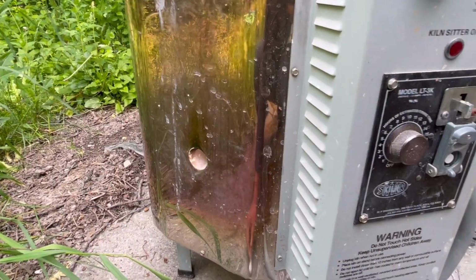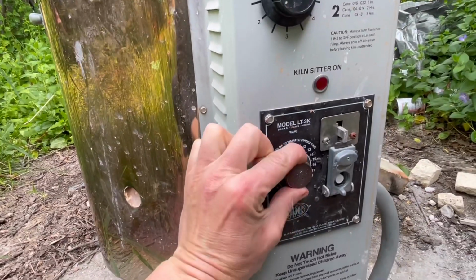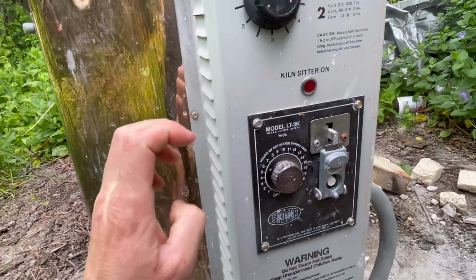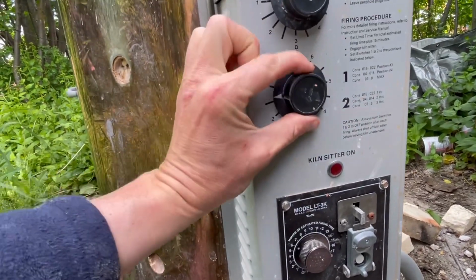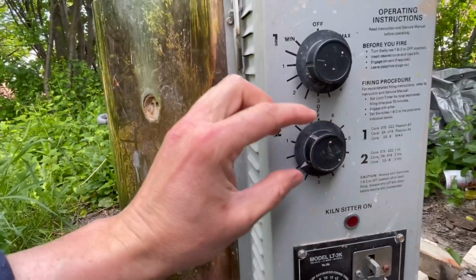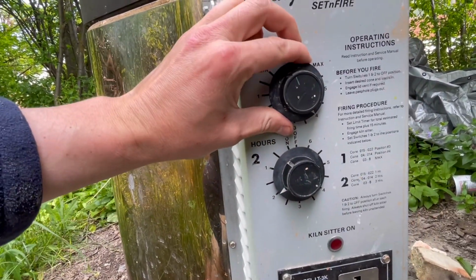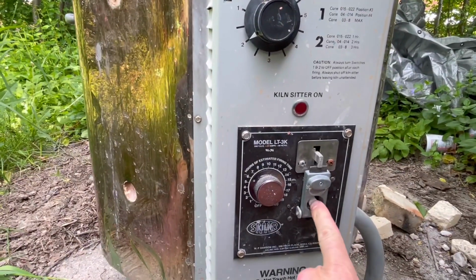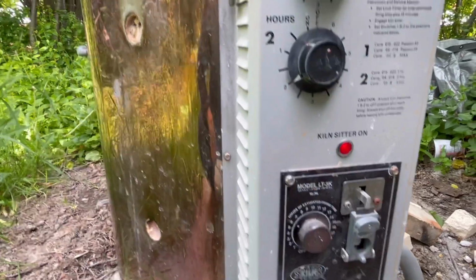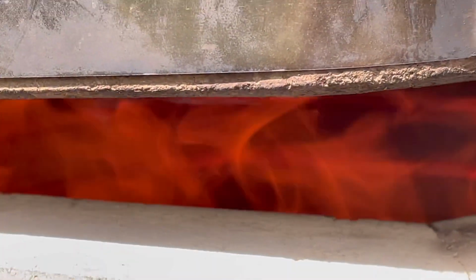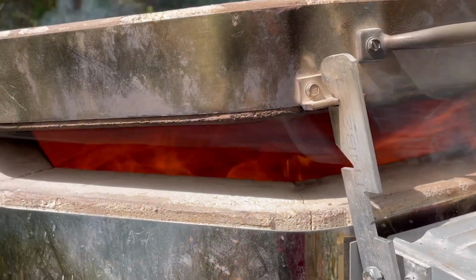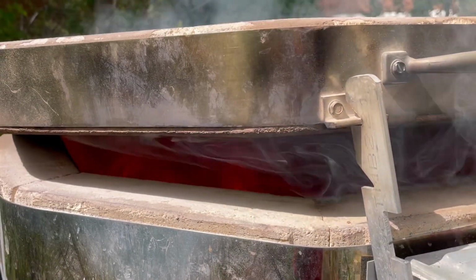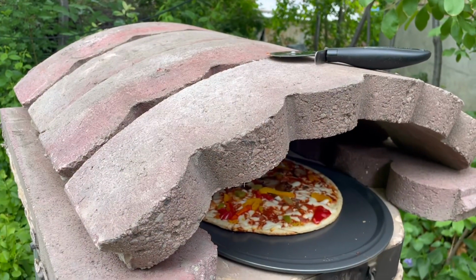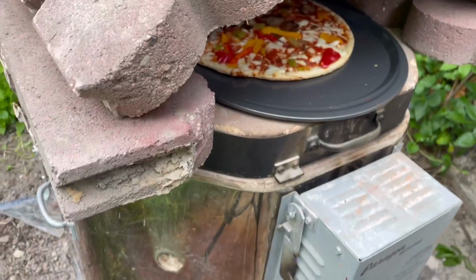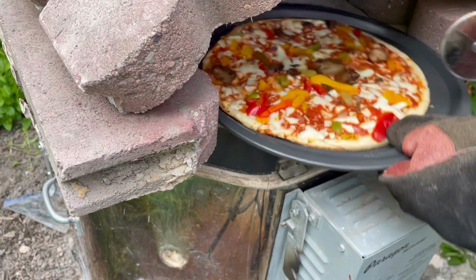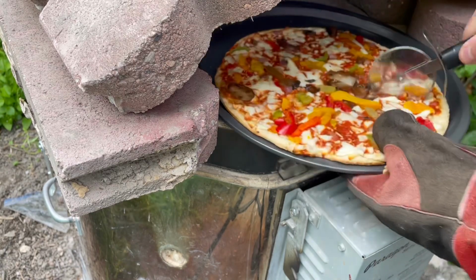Let's pull out one of the vents so it can get some air. It's probably going to take around 6 hours for this. Let's give us a couple of hours of preheat so I don't explode my pottery in there. Turn that down to 4 and go. This was smoking a bunch, so I opened the lid a crack to let air in and burn away the vapors from the bones. I thought that since I'm producing a lot of heat, I might as well stack some blocks around it and make use of it. Made me a little pizza oven on top of my kiln.